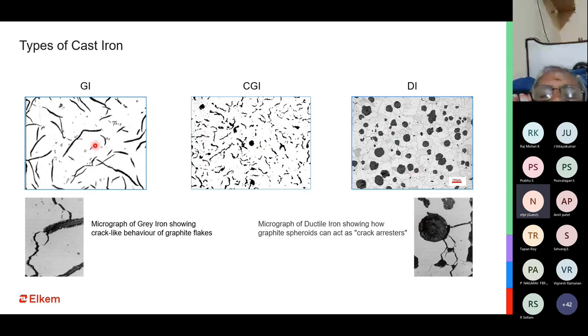Now, we did not stop there. Of course, we tried to form a kind of iron or casting which should have the combined effect of both types of iron. And that is what CG iron is, with a controlled amount of magnesium, with a very controlled treatment, where we do have flakes, but they have rounded ends, and we also have some graphite.